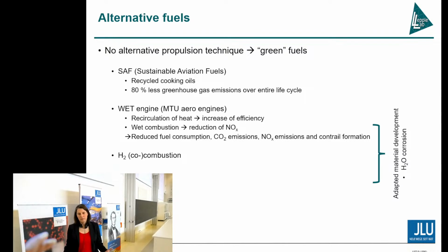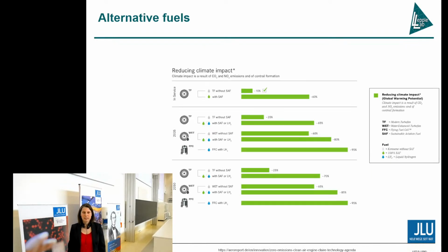And what actually might replace the fossil fuels will be the hydrogen combustion. However, for both the wet engine and the hydrogen combustion, the materials have to be actually adapted. So for materials development for these new types of gas turbines, they have to withstand water corrosion, which is very corrosive at this high temperature. However, with these new techniques, I have a slide here which shows actually the reducing climate impact by introducing the new techniques like the SAF or then the wet engine or the combustion or co-firing of hydrogen or totally use of hydrogen.